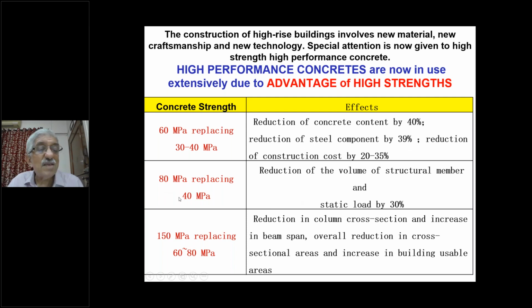If we are replacing 40 megapascal by 80 megapascal concrete, then reduction in volume of the structural member will be higher. Static load is reduced by 30% in the design. If 60 megapascal is replaced by 150 megapascal, reduction in column cross section and increase in beam span, overall reduction in cross sectional area and increase in building usable area.